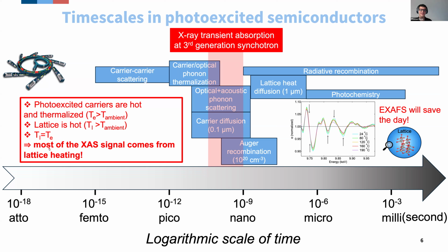But the message here is that most of the signal that we actually measure when we do these experiments at synchrotrons actually comes from lattice heating. And the fact that the EXAFS have such a high sensitivity to this effect will actually save us, because we will be able to tell much more than just that there is lattice heating in our semiconductor.